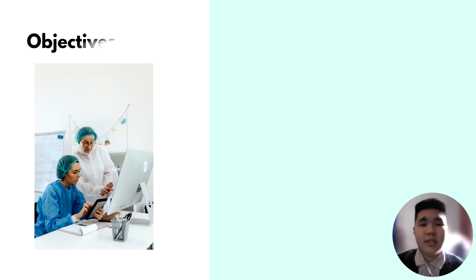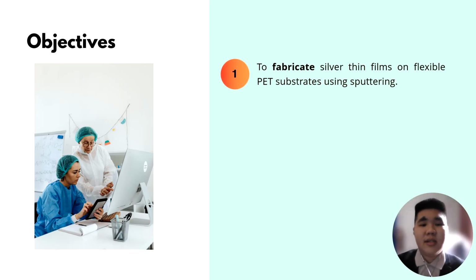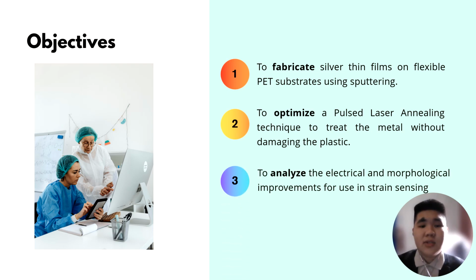Therefore, our research solved this challenge with three key objectives. First is to fabricate silver thin films on flexible PET substrate using sputtering, second is to optimize the pulse laser annealing technique that treats the metal without damaging the plastic, and thirdly is to analyze the electrical and morphological improvement for use in strain sensing.